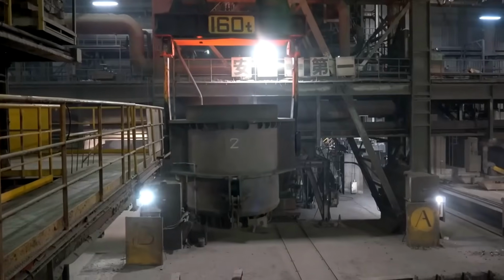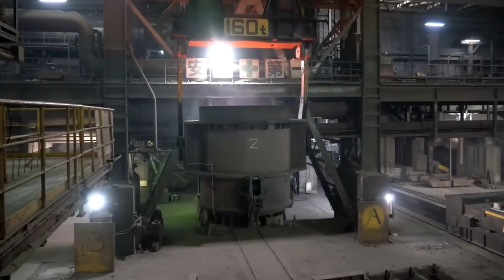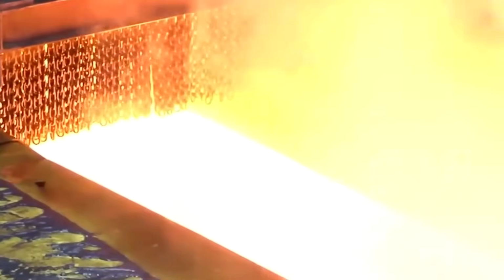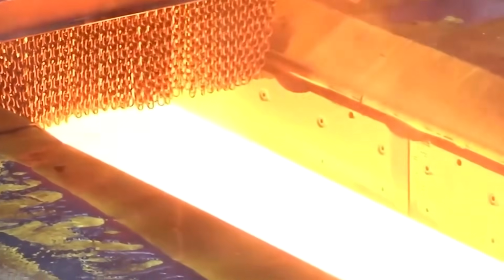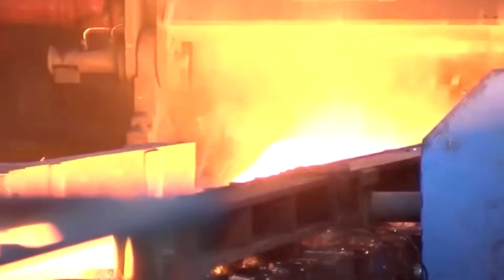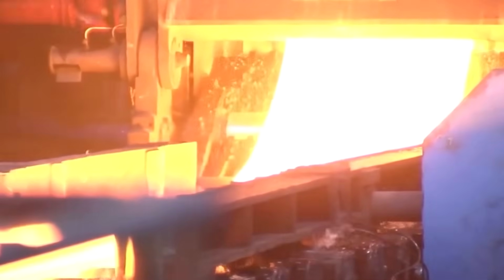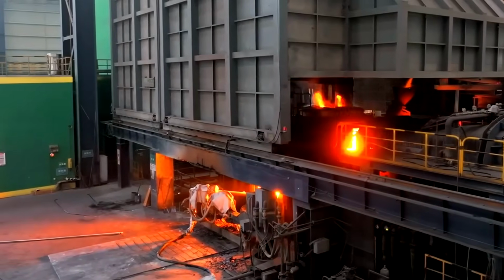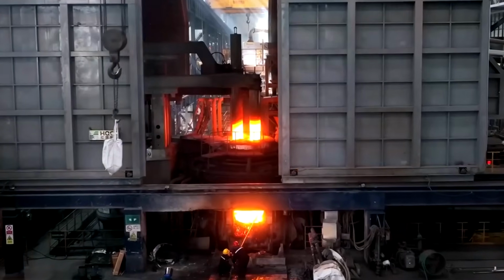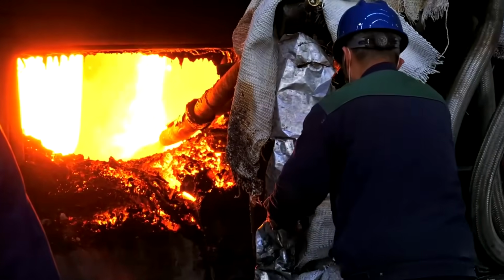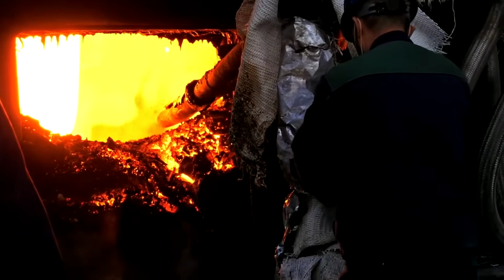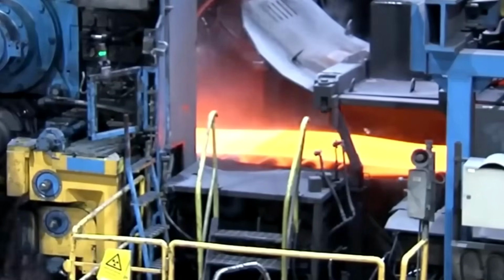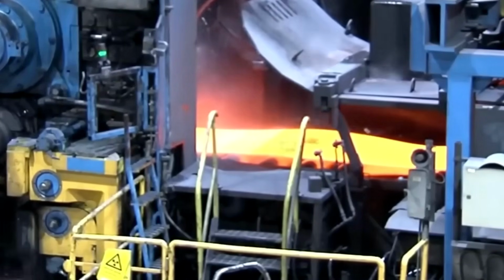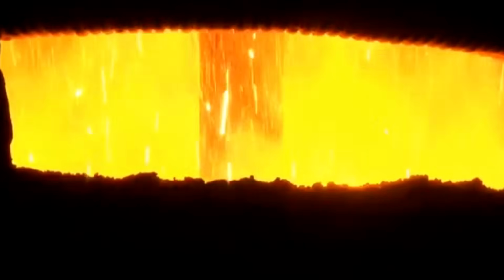Molten steel is poured from the electric arc furnace into a continuous casting system to begin the transition toward a solid form. The camera glides along the molds where the liquid flows through water-cooled channels. It is visible how the metal gradually solidifies into glowing red square or flat steel billets as the exterior temperature drops. The billets are cut to standard lengths using automated saws once the required level of internal solidity is reached. But this is just the beginning.